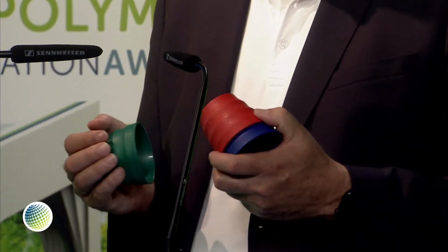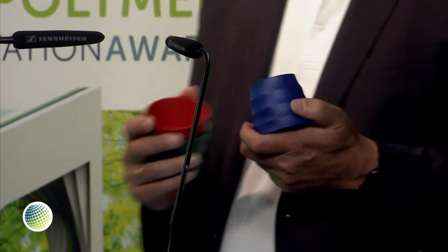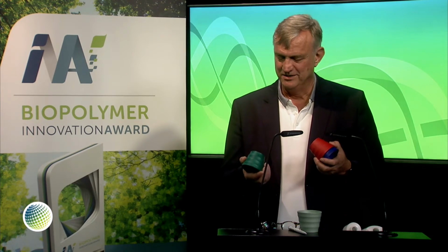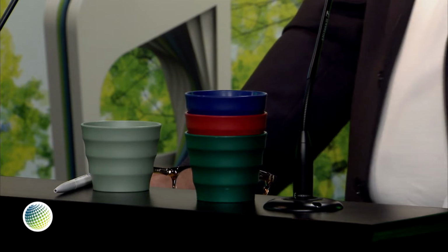And in fact, we saw the same effect: the gate temperature is quite crucial, and you have to observe the gate temperature very closely. We see this also on our cups. If there's a slight change of temperature, we immediately get a white spot on the bottom. So this is the same from expert to expert. I mean, you are the better expert in hot runner, of course, but this is something that we also realized in our production.